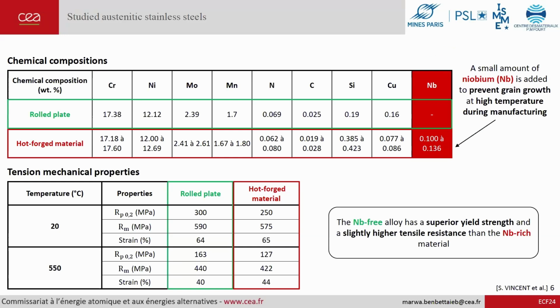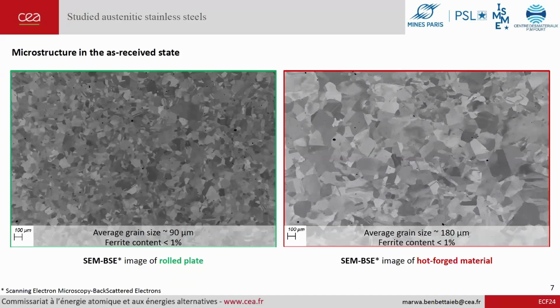For the tensile mechanical properties, the niobium-free alloy has a slightly higher tensile resistance and a superior yield strength compared to the niobium-rich alloy at both room and high temperature. If we take a look now at the microstructures in the as-received state for the two alloys, we can note here a typical equiaxed microstructure of 316LN alloy with 90 micrometer as average grain size, against higher grain size for the niobium-rich alloy, which is twice the size of the other alloy. And here we can note also the presence of sub-grains.